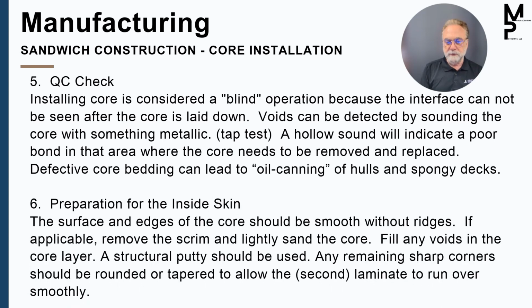Okay, now once we've checked that, we want to make sure the top surface is ready for lamination. So one good thing I like, if it's a contour core, you can remove the scrim material and sand it. You don't need that scrim anymore. If you look in the lab when we do testing, often we see the laminate fail. When we pull these apart in a test, the scrim side tends to fail more than the bedding side. Well, we pay a lot of attention to the bedding side because it's the blind connection. Then we laminate over the scrim. If you remove the scrim, you get a little bit better bond, and it's worth it. Okay, so make sure that your edges are good. If you've got ramps, corners, things like that, you can use putties, you can sand them, or you could again use those wedges we talked about.